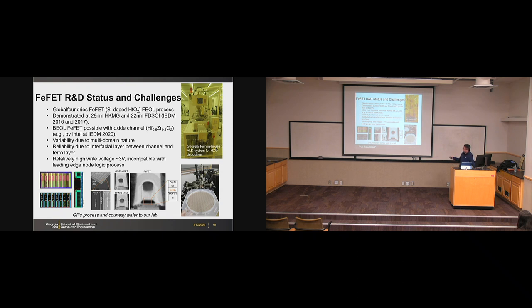And the challenges associated with new technology, of course, first variability for any emerging technologies. And especially for the ferroelectric, the challenges with the multi-domain nature. So you have many domains due to the grain variation, grain boundary, and so on. So then they will cause some variations from device to device. And also the reliability will have some challenges, especially if you have some interfacial layer between the channel and the ferroelectric layer. For example, the channel is silicon and the ferroelectric is hafnium oxide. So the interface might be silicon dioxide. This silicon dioxide may get defects when you cycle the device. That will cause a lot of traps and then that will create noise and endurance degradation, retention issues and so on. So there are challenges with the reliability.